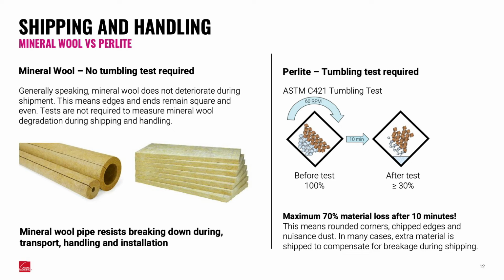So that basically means if you started out with a pound of material at the beginning of that 10 minutes, you're allowed to have 1/3 of a pound left after that test has been run, which really means you have 70% of material that's dust, and that's going to be chipped corners, edges, nuisance dust, essentially material that you can't use. In many cases, you might have to ship additional material to compensate for that breakage as it's damaged from point A to point B.